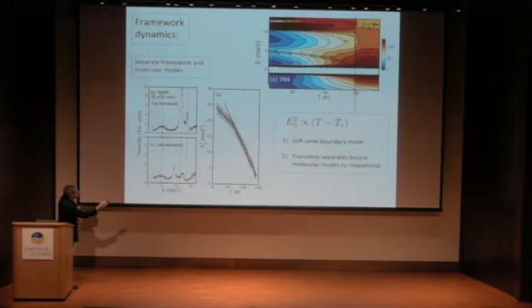Now, you can plot the temperature dependence of this mode. What you find is that it softens towards this transition. You can fit it to a Cochran law and find that it scales exactly as you might expect. From calculations, we know this is a zone boundary mode, and that it is associated with this phase transition. So what we see here is a softening of this framework mode right to 150. One thing that is interesting is that above 150 Kelvin, you lose these nice sharp hydrogen modes, and they become very broad in energy and basically overdamped.